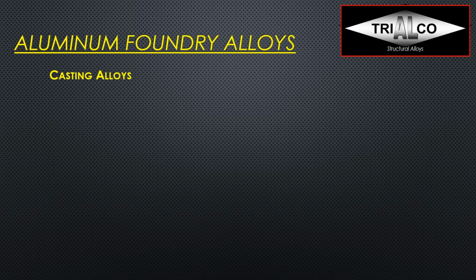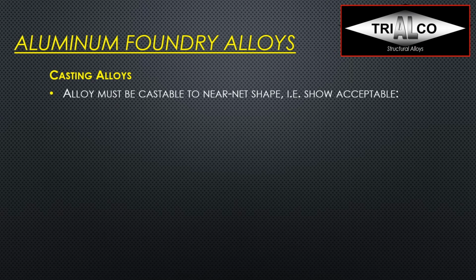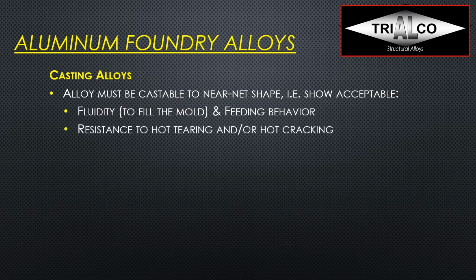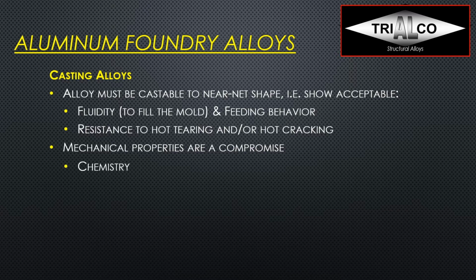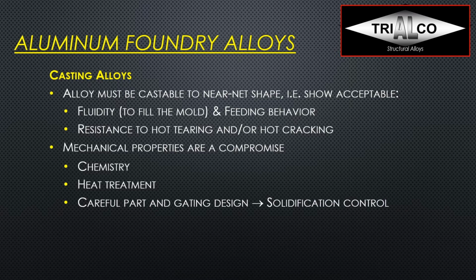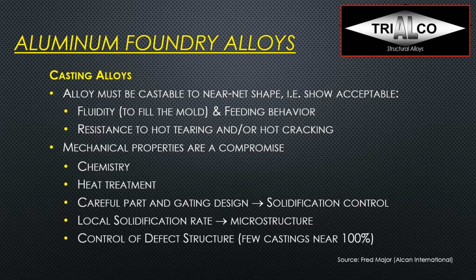Now with casting alloys, as I said, it's kind of an engineering compromise because the alloy must be castable to near net shape. So I'm going from liquid to solid in the final state with nothing in between. So I need fluidity. First of all, I need to fill the mold, and then I need to be able to feed it during the solidification. So I need good feeding behavior. I need resistance to hot tearing and hot cracking during the solidification. My mechanical properties are really a compromise between chemistry and impurities, heat treatment, careful part and gating design, so that means solidification control, and the local solidification rate, which gives me the microstructure. And we have seen that with a higher freezing rate, I will get a finer microstructure, and that will give me better properties, especially ductility. And then control of the defect structure, because very few castings are 100% perfect.